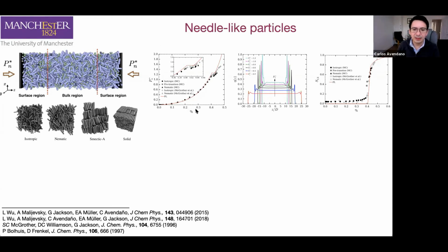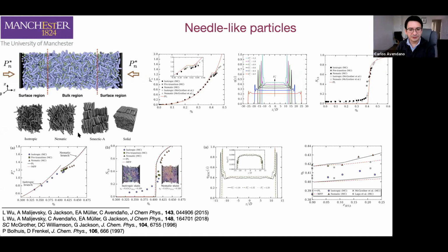So in this phase diagram, on the x-axis we have the volume fraction. On the y-axis, we have the pressure. And we can observe that as soon as we increase the pressure, the density also increases until we observe the transformation from the isotropic phase to something called the nematic phase, which is given here. And at even higher densities, we should observe the formation of the smectic phase. Just with this simple technique of adding two hard walls, having a long system with the walls being far away, that means that we can have a bulk region that we can use to characterize the system. And we did it for the pure components, which are the results here at the top, but also we did it for the mixture between the cylinders and the spheres, and the phase diagram is here. So without going into too much detail, the only thing I wanted to show you here is that geometrical confinement can also be used as a technique to study the phase diagram of systems that are intrinsically complicated to study because the surface tension is very low.